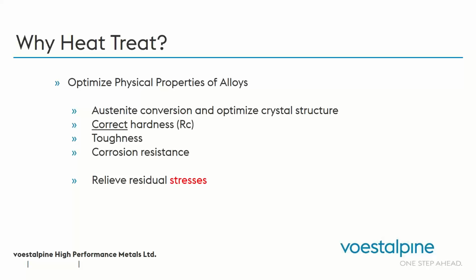So please make sure that no matter what heat treater you decide to use, they follow the procedure as outlined in the Uddeholm or Bohler or no matter what manual, as outlined, that they follow that procedure. And one thing that also, by following proper procedures, you can get corrosion resistance. And corrosion resistance is not as important in die casting, but there are situations that it really does come through critical. Now, one thing that heat treaters can do is relieve residual stresses in your block.